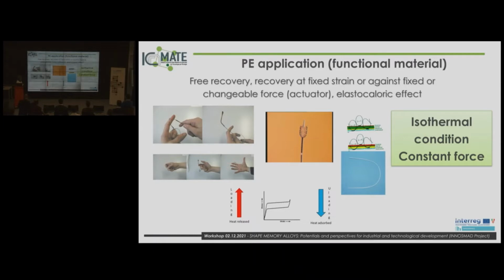One interesting and very recent application is the elastocaloric effect. When we consider the pseudoelastic deformation, we consider the flag-shape curves. And in this case, when we have the loading part of the curve, the material transforms into the martensitic state and releases heat. And then when the martensitic state comes back to the austenitic phase, the material absorbs heat. Then we have a material which, by deformation, releases and absorbs heat.